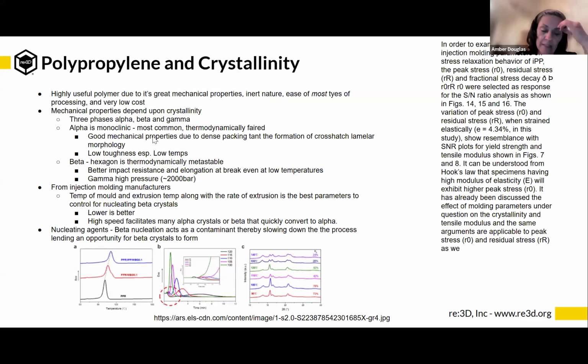So this is something I've been studying lately because I have an interest in this. We've been able to successfully print here at re:3D pretty nice parts, but to really get it consistent and to really own this type of printing, you would need to understand the alpha, beta, and gamma crystalline phases that it has. And a lot of people, if you buy a filament, for example, it's going to have some sort of beta nucleating agent in there. Beta nucleating agents are just a different type of crystal structure than the primary one that's more thermodynamically stable. If you print with neat polypropylene and you get a print, it's almost always going to be alpha. But beta has larger crystals, they take a lot longer to form, and so they give you more time to print with, basically, before it pops up or starts curling up at the edges.